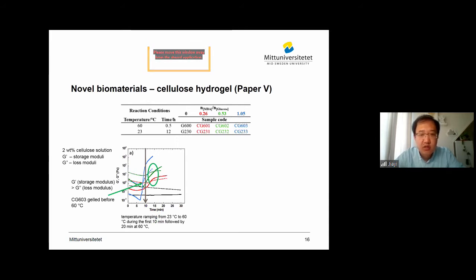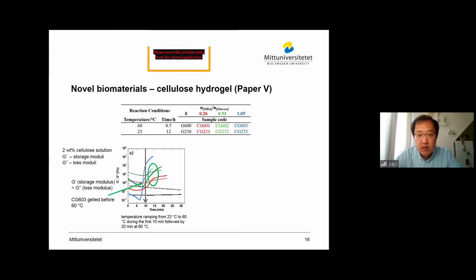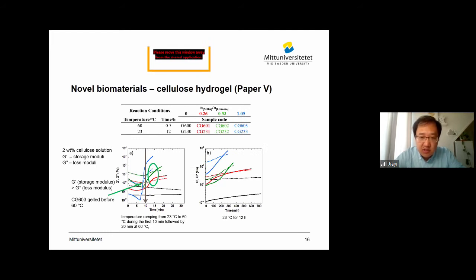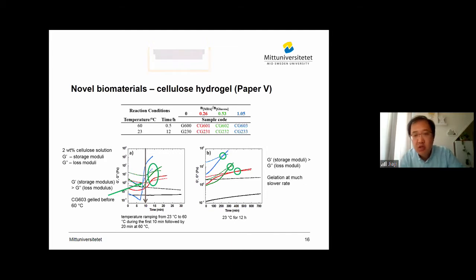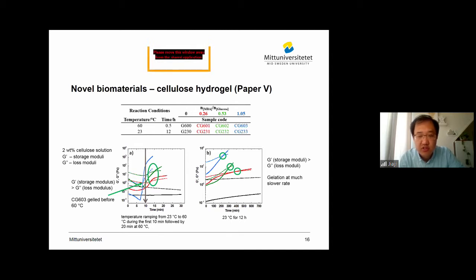For the other two samples, which have a relatively lower concentration of cross-linker addition, the gelation happened after the temperature reached 60°C and equilibrated for several minutes. For the samples on the right side — hydrogels cured at 23°C for 12 hours — with different amounts of cross-linker addition, the behavior is quite different. With the highest addition, it has the shorter gelation time, and lower addition has longer gelation time. The gelation time of the samples ranges from about three hours to up to six hours.